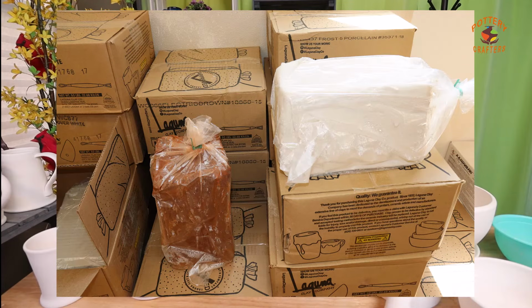The type of clay you choose is also important. Different clays have different shrinkage rates. The higher the shrinkage rate, the greater chance of your clay cracking, because the clay is moving more. Porcelain can shrink anywhere from 12 to 20%. The shrinkage rate of stoneware is around 12 to 14%. And earthenware has the least amount of shrinkage with about 4 to 7%.